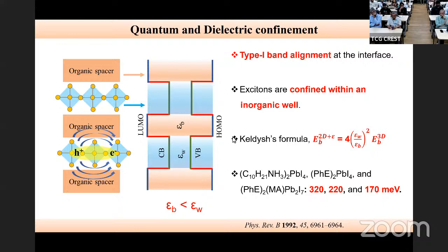And it turns out that many of these compounds that people make, there are 3 examples cited here, have their excitonic binding energy more than 100 milli-electron volt compared to the 3D counterpart that I told you is in the order of 30 milli-electron volt or 60 milli-electron volt. And that's bad news, because both the band gap increasing and excitonic binding energy increasing are the prices that you are paying, with the hope that we'll be able to design something that will have the stability with respect to moisture.